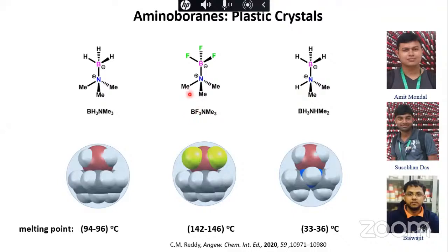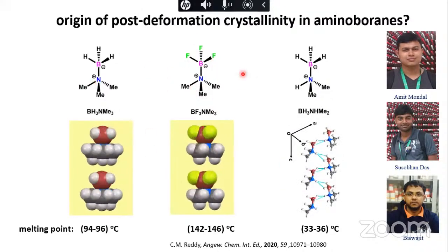So in this case, instead of 3 methyls, you have 1 NH group and 2 methyls. Okay, and then here you have hydrogen. If you compare this with this one, you are only removing 1 methyl and putting a hydrogen. Since this is highly positive, this hydrogen is also highly positive. And since this is negative, this hydrogen is also almost negative. Because of this, there is a dihydrogen bonding in this case between adjacent molecules. But in this case, you don't have any strong hydrogen bonding. Intermolecular interactions are very weak, although you have ionic attraction. But you don't have any strong hydrogen bonding interactions in these 2 cases.